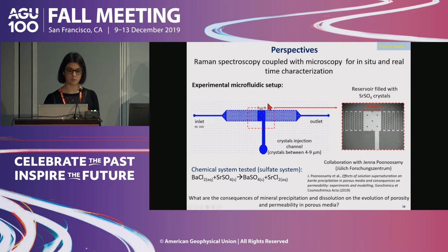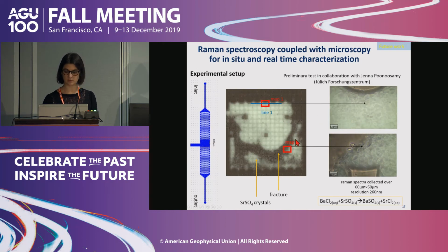So that's why we decided to perform microfluidics experiments to get more insight into the mechanisms in real time and in situ. So this is the microfluidics setup. We have a reservoir here, and in this reservoir we inject crystals of strontium sulfate, and then from here we inject barium chloride from left to right. So this is how it looks with the crystals. This is the reservoir with the crystals of strontium sulfate. Here we have the presence of a fracture, and now we inject some barium chloride from inlet to outlet.